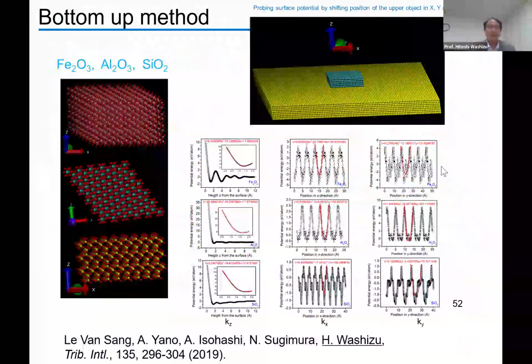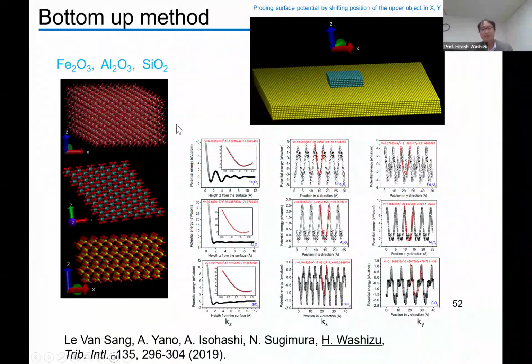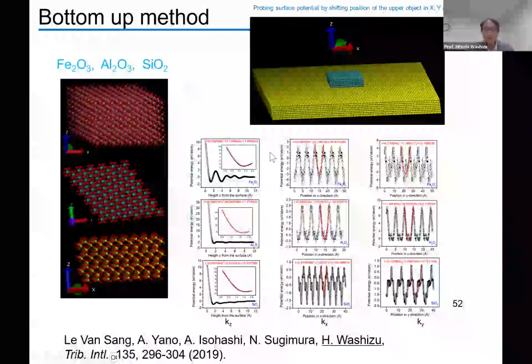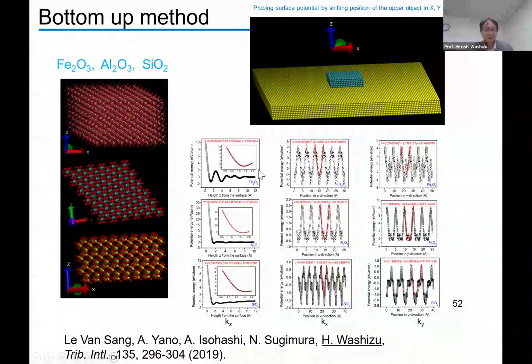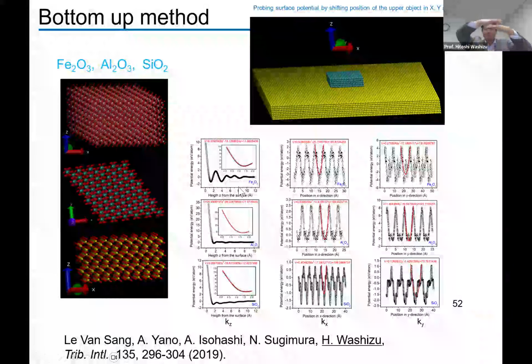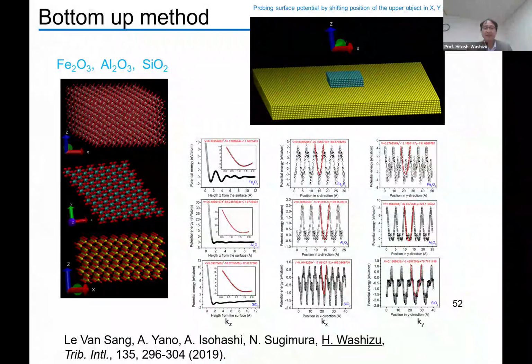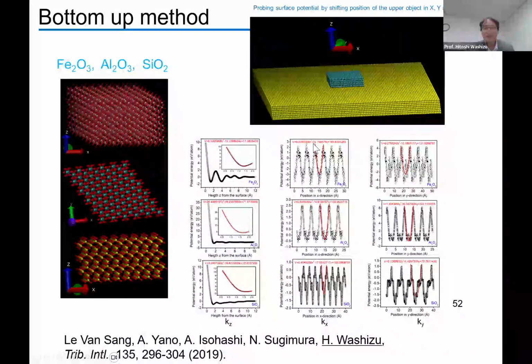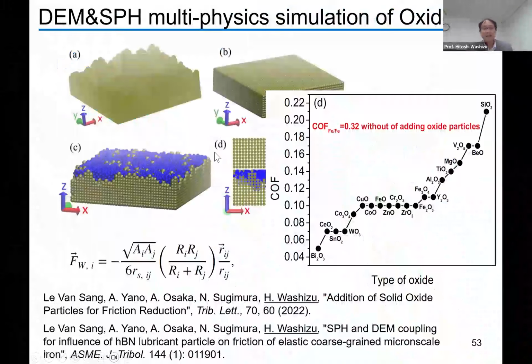fluid motion. Okay, and in this case, bottom-up simulation can handle the surface interaction between these three materials. We run some molecular dynamics simulation and calculate the force interaction correctly, and we just want to obtain the force interaction parameter, shown by this red line. Then we put this red line into this kind of SPH simulator, and then we could reproduce some friction, okay? And this method is extended to DEM and SPH.